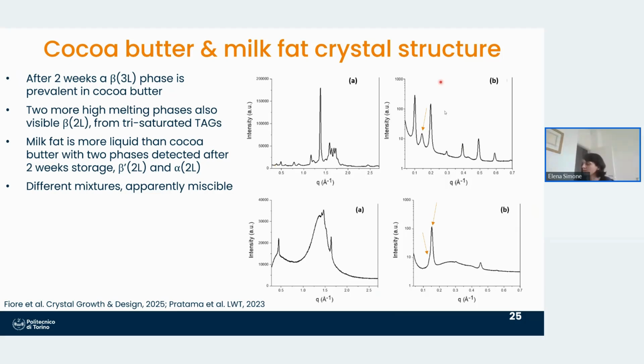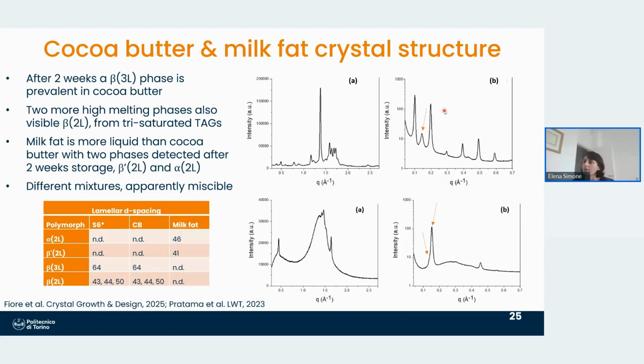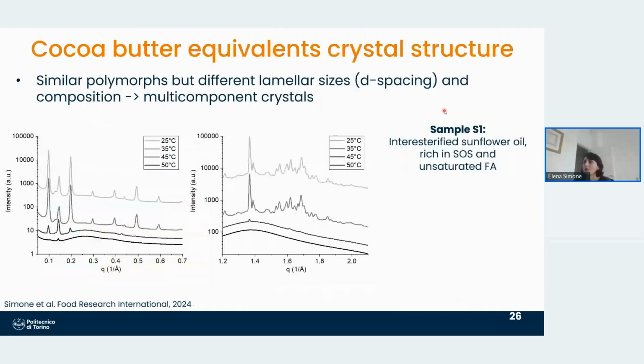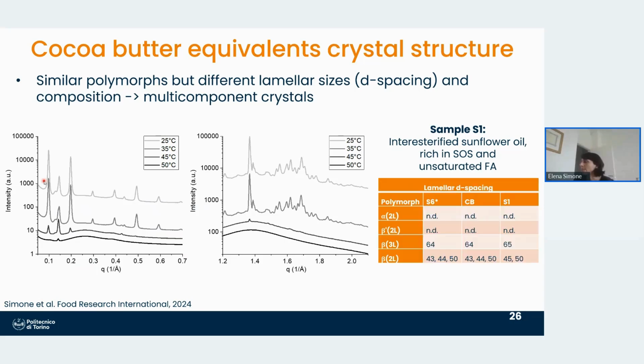Again, from the position of these peaks, we can get the lamellar spacing. So I've tried to look at many different cocoa butter equivalents. I'm not going to show you too much in detail here, but if we only look at the SAXS region, where we can see the presence of the different phases, we always have the characteristic polymorph of chocolate and then extra phases. And those can be a problem when we start mixing in a formulation, because they are a little bit unpredictable, especially in terms of stability.